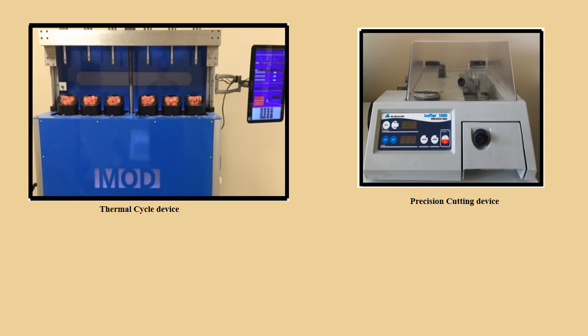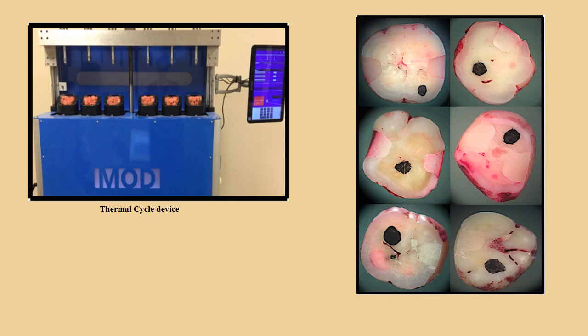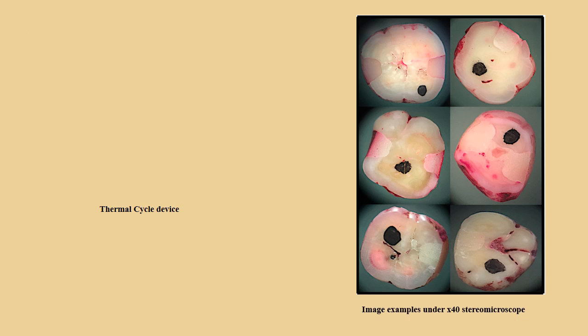The specimens were stored in distilled water for 24 hours and were immersed in basic fuchsin solution for 24 hours. 2 mm sections consisting of the occlusal-gingival middle third of the tooth were taken with a precision cutting device and bilateral diamond disc under water cooling from the teeth. Microleakage was evaluated under a stereo microscope at 40 times magnification. SPSS software was used for statistical analysis.